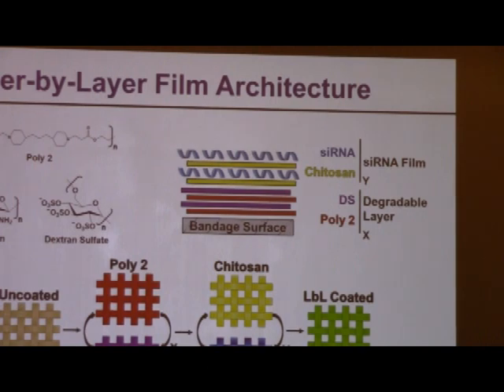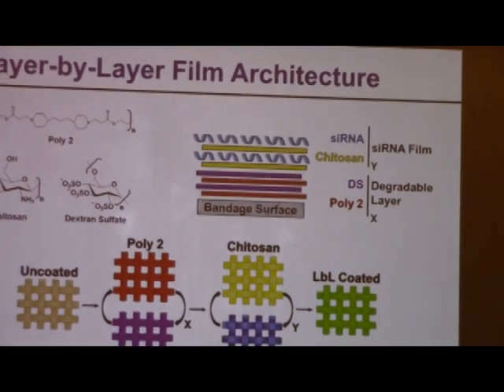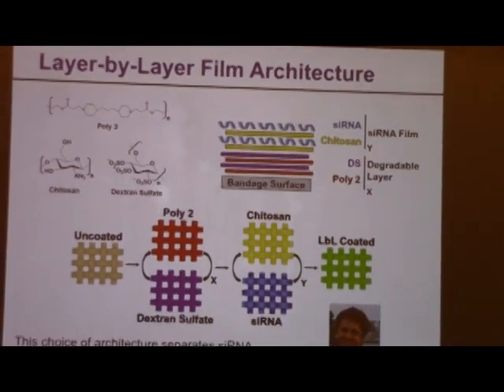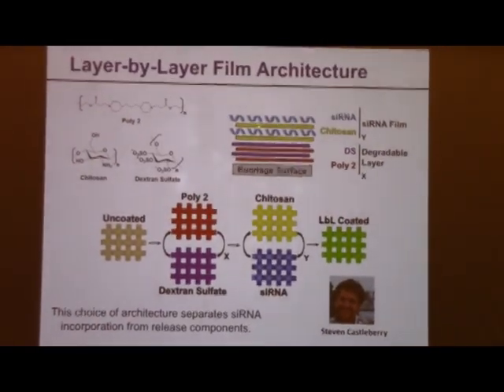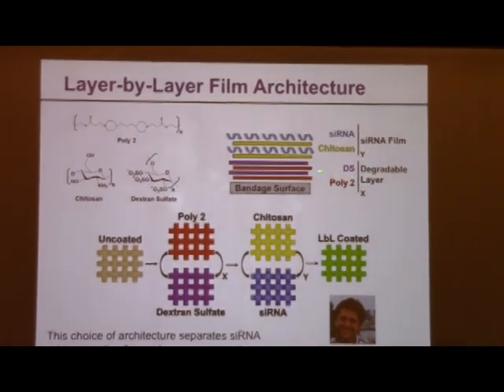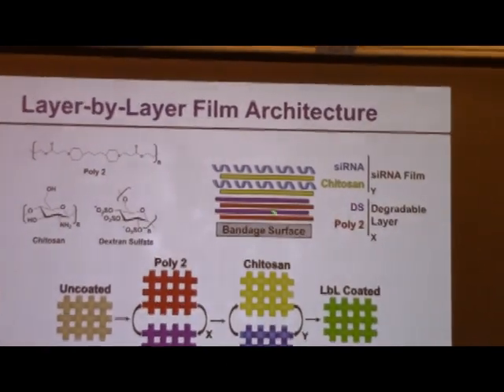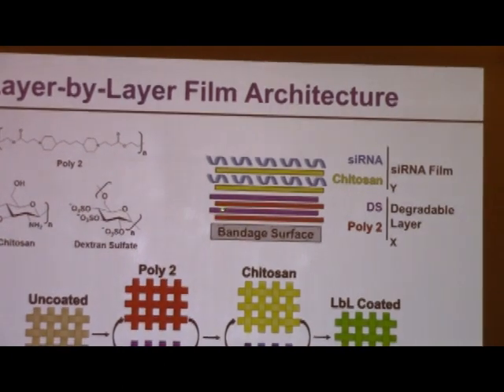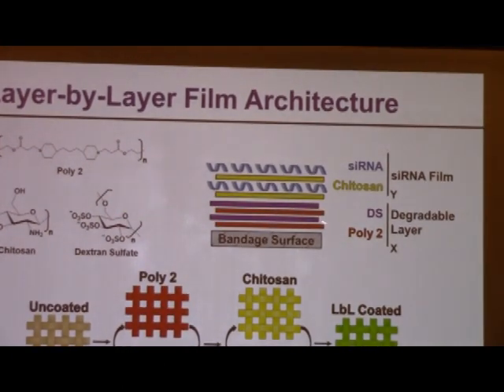The only problem is that chitosan doesn't break down anywhere near the time frames that are relevant to this wound healing project. If you're interested in breakdown over a period of a few weeks, chitosan will remain stable in the body for a few months. So underneath these layers of siRNA and chitosan, Stephen built a second set of layers that were designed to break down. And these contain one of the degradable polyesters we talked about. This one's called poly2, layered with dextran sulfate, which is just a very simple polysugar.